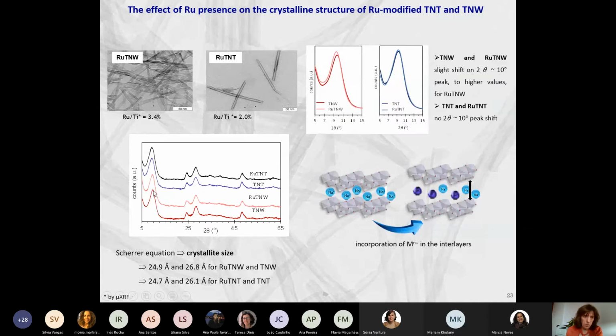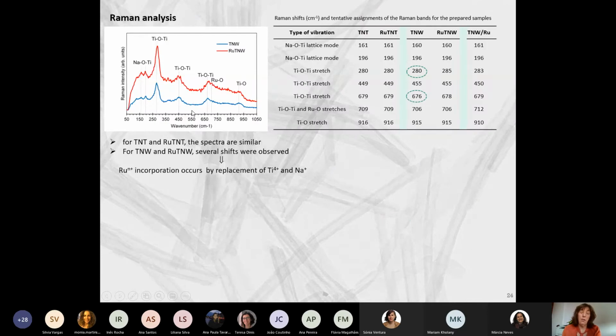But if I focus on this peak at 10 degrees 2 theta, I can see that, in fact, when we have the nanowires, we have a shift in this value. And this tells us that we have changes in the interlayers. And this means that we have some ruthenium here in the interlayers. And that's why our distance here is different, okay? For the case of titanate nanotubes, we have no changes in these parameters, so we are not expecting to have ruthenium in the interlayers. Then we decided to analyze the Raman results.